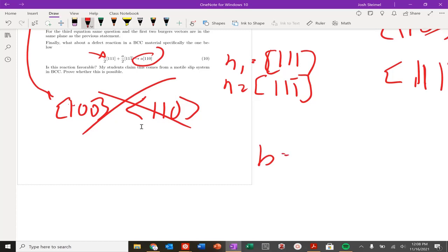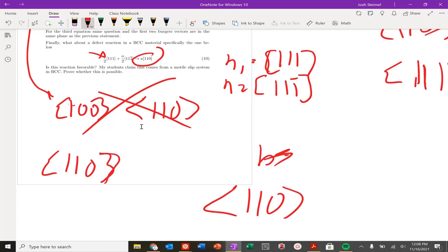Actually, I can answer this right now. So my slip system for BCC is what? I need to be in the 1, 1, 0 plane, and I need to be in the 1, 1, 1 direction. So already, I am not going to be motile, because I see that reaction coming here.